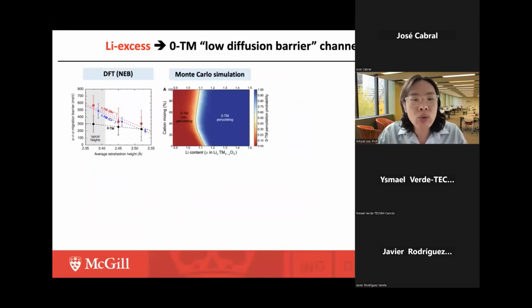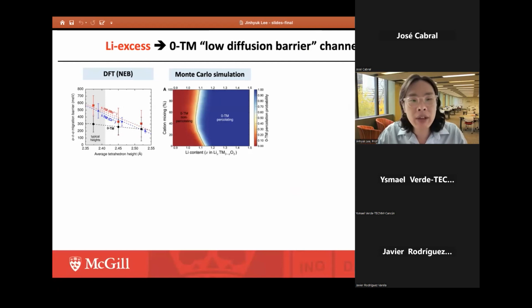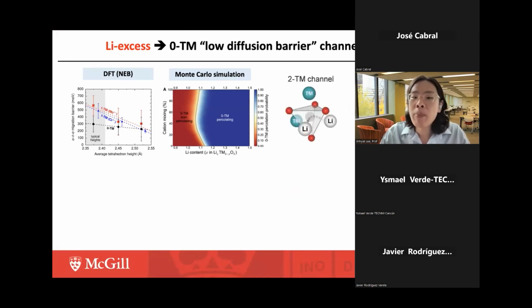To understand this counterintuitive behavior, we did a theoretical study using both density functional theory calculations and Monte Carlo simulation. In this study, we found there is a general lithium diffusion pathway, and we realized that geometrically there are 3 types of diffusion channels, namely 2TM channel, 1TM channel, and 0TM channel. In this naming scheme, the name refers to the number of transition metal cations face-sharing with the tetrahedral lithium, which becomes the activated lithium diffusion site.